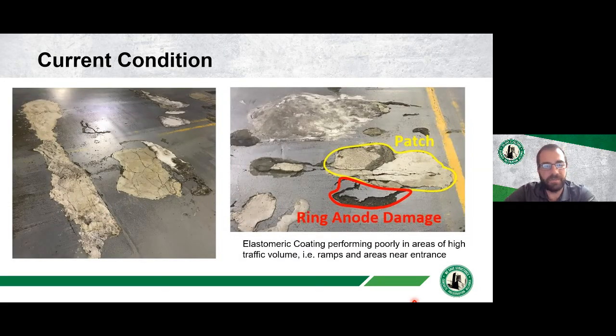And so this is kind of what the condition of the structure looked like. We see a couple of things here. We see very old patches that were done. So clearly they've had some delamination and spalling and they repaired things. Now these patches are not very well done. We don't see a lot of straight edges, 90-degree angles. These are what we would consider poor patching, so not very good at effectively extending the service life of the structure. We also see patching and adjacent to patching new damage. So something we would call the ring anode or halo effect. This is where you have chloride-free concrete next to chloride-contaminated concrete, and that creates a corrosion cell across that boundary. So now you start getting corrosion occurring around the old patches.